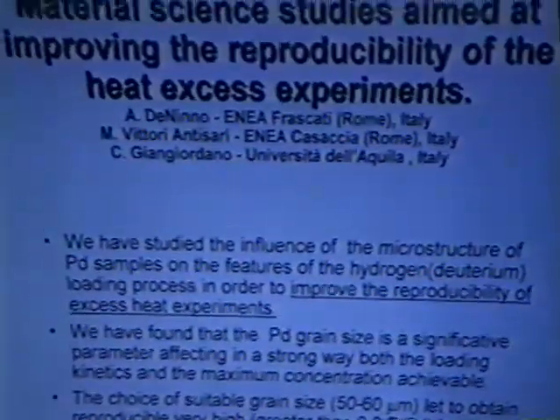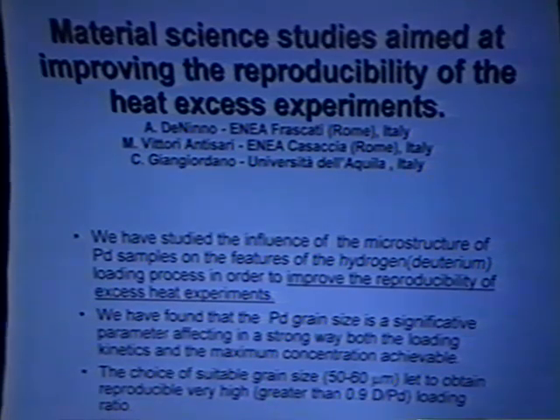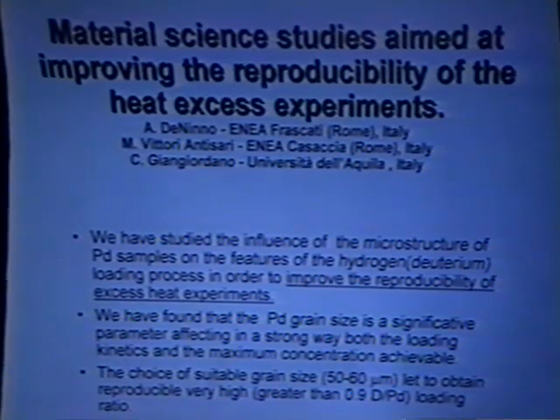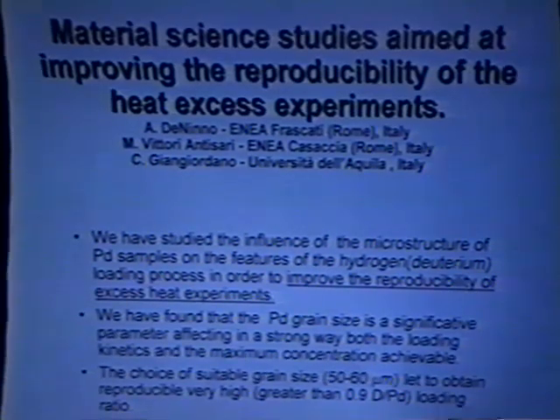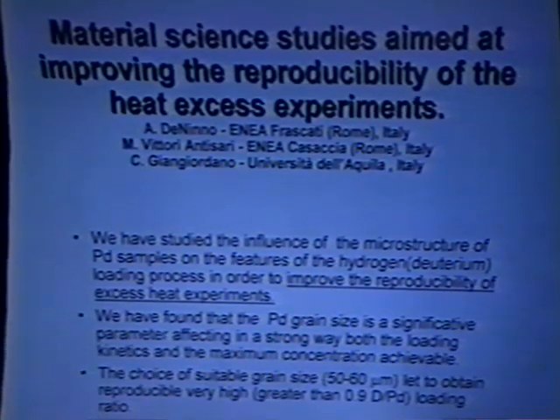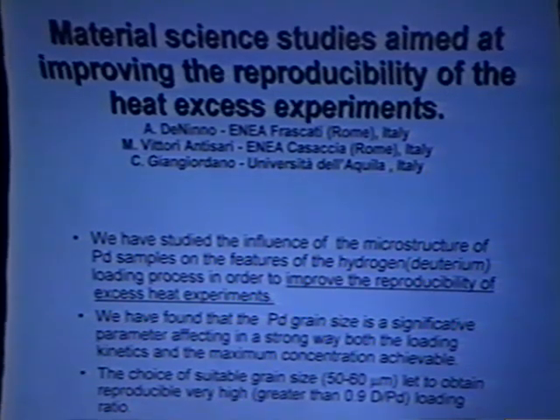We did a study on material science, whose main goal is to improve the reproducibility of heat excess experiments. We have studied the influence of microstructure on Pd samples, and we did a systematic study to understand the mechanism that improves the loading in palladium. What we found is that there is a correlation between the loading ratio and the preparation procedure of the material.